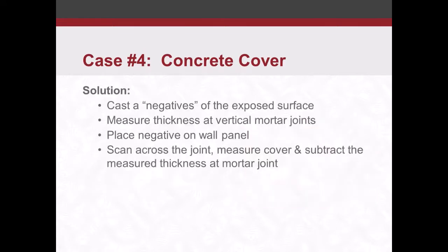So we had to figure out something else to do. We put our heads together with a bunch of different people, and we came up with a solution of match casting, casting a negative of the exposed surface on the mortar joints. I think there were 5 mortar joints, two on the top course, 1 in the middle, and 2 on the bottom course. So we had 5 of these panels that we cast, basically using the precast panels as a mold. We cast another panel on top, and then we took those panels out to the field. We put them on top of the mortar joints, and we did our scans.